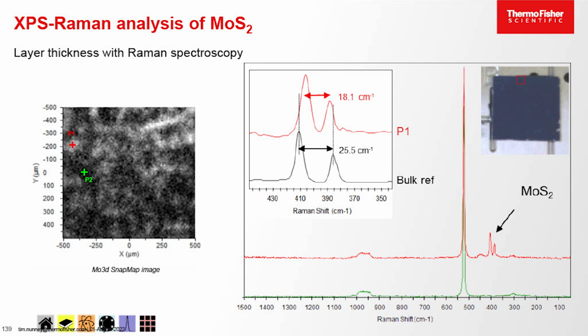So the next step is to do a bit of Raman on it. And again, like graphene, molybdenum disulfide is a very good Raman scatterer. And actually, the interesting thing is the separation of the two peaks we get due to molybdenum disulfide is determined by the number of layers we have in the structure. So the fewer layers we have, the smaller the separation between these two peaks is. So this is a bulk reference of MoS2, and that has a separation of about 25 wave numbers. And at P1 here, where we have a nice strong molybdenum disulfide signal on our sample, we just have a separation of 18 wave numbers. So that suggests that we've got something close to a single atomic layer, at least at that point.